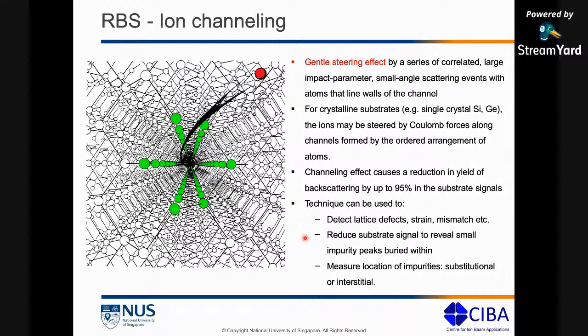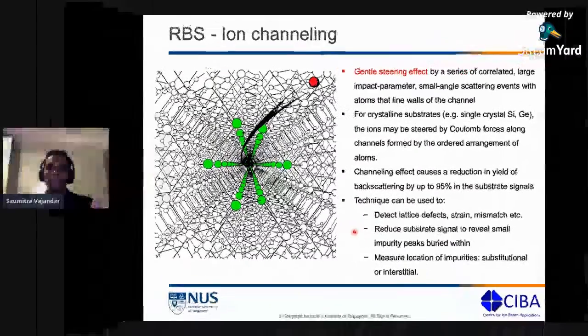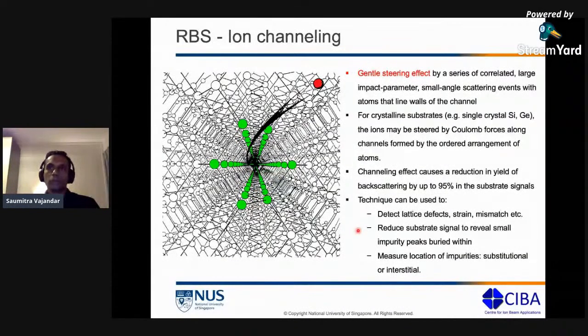But if, let's say, we have a single crystal sample, not gold, let's say we have silicon, which is a single crystal. When I say single crystal, that means it has a crystalline structure to it. So let's say I'm now able to align the atomic rows of this single crystal to the incident ion. What's going to happen to the incident ion? The incident ion is basically going to go straight into these atomic rows or these channels, right? So that, in layman's terms, is ion channeling. You are taking the incident ion and aligning the single crystal substrate in such a way that the incident ion channels through the atomic rows of your substrate. So it's basically a gentle steering effect. In scientific terms, ion channeling is a gentle steering effect by small angle scattering events with atoms that line the walls of the channel.